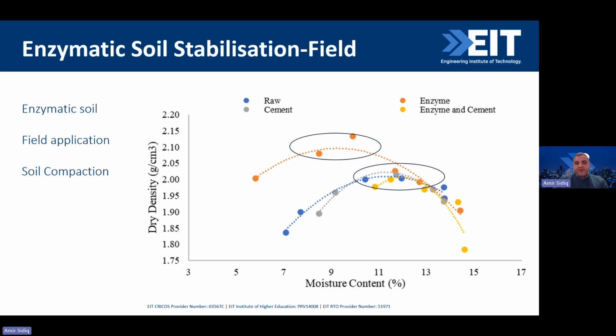So by using these four mixes, we have the raw, the enzyme, the cement, and the enzyme added with cement. You can see for the cement and the raw materials, there is a very small difference in the moisture content, and even in the dry density. But when we use the enzyme itself, it reduces the moisture content and increases the dry density quite highly compared to the remaining mixes. You can see the impact of the enzyme in this case.